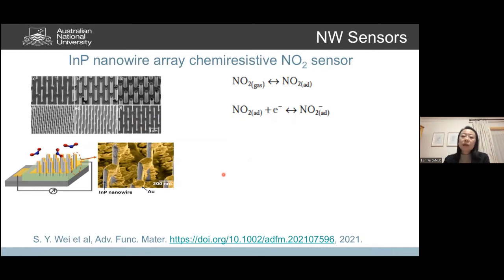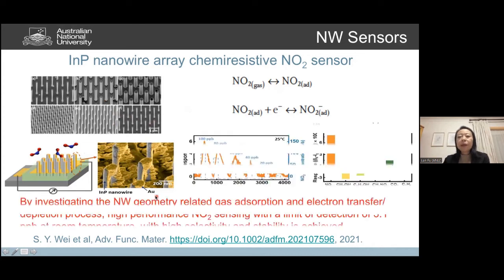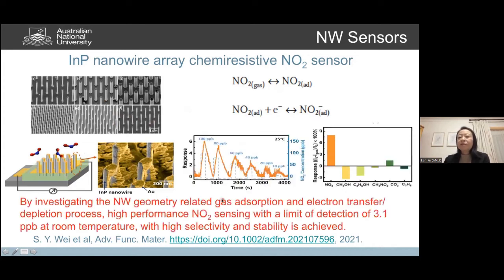So this adsorption, and the charge transfer, lead to a conductivity change of the nanowire. This is how we can detect it: by detecting the current change, we're able to sensitively detect nitrogen dioxide adsorption. To fabricate this nanowire device, we also use tilted angle gold deposition, so we can expose half of the nanowire surface to the nitrogen dioxide adsorption to achieve this sensing. And it turns out that this nanowire-based sensing device is highly sensitive.